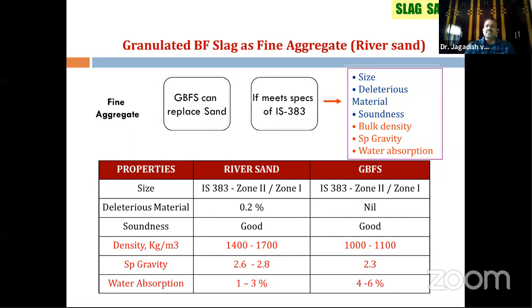And specific gravity is also less when compared with the natural river sand. It is 2.3. Water absorption is also more, that is 4 to 6%. So if density is less, specific gravity is less, and water absorption is more, that means some kind of pores are present in this granulated blast furnace slag material. That means some kind of vesicular structure which contains small pores in this particular slag.